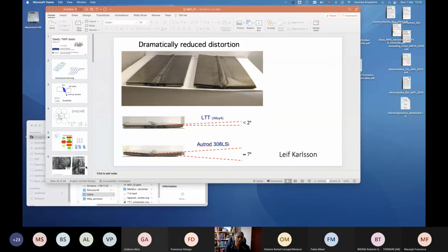Yeah. So I'll share the screen again just to show you. What I meant was, these regions in which you can get dislocation plasticity decrease as the amount of twinning increases. Effectively that's reducing the regions of austenite, starting with a coarse austenite grain. It's subdivided into smaller and smaller regions as deformation twinning progresses, and that is the dynamic grain refinement by partitioning with twinning.